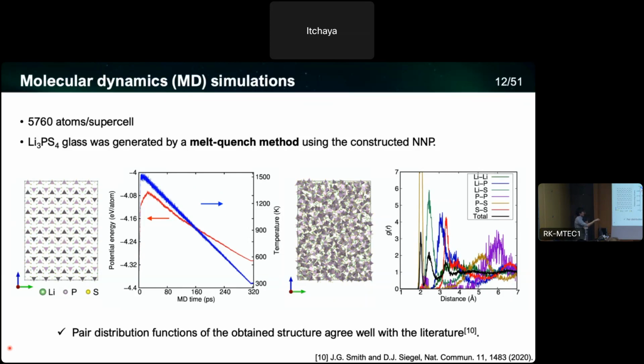We evaluated the pair distribution functions for the obtained distorted structures. I'm sorry that this graph is busy, but if you look at those black lines, we have no specific peaks after 4 angstrom. This indicates that the obtained structure is glass. There is a study doing ab initio molecular dynamics simulations, and they also presented the pair distribution functions. When we compared them, they agreed with each other, which means that the neural network potential that we have is quite accurate and can reproduce the data calculated at the density functional theory level.